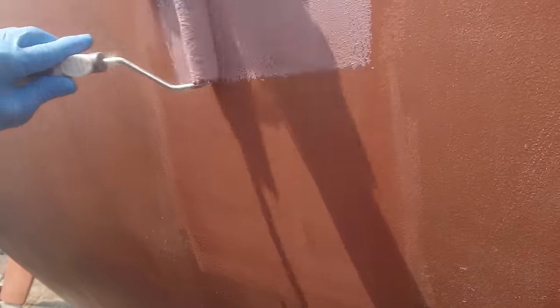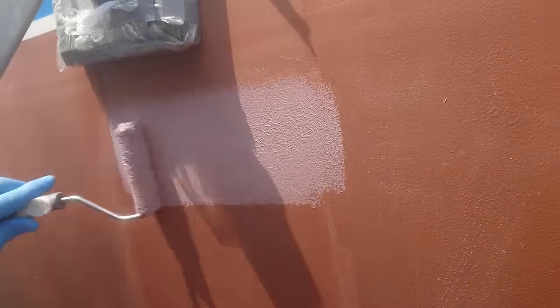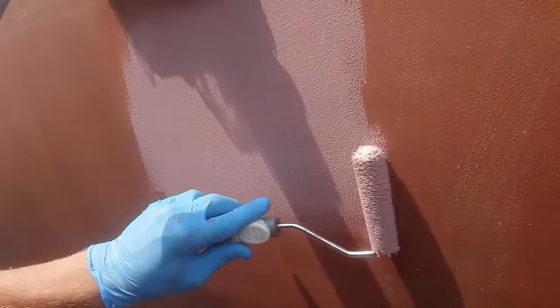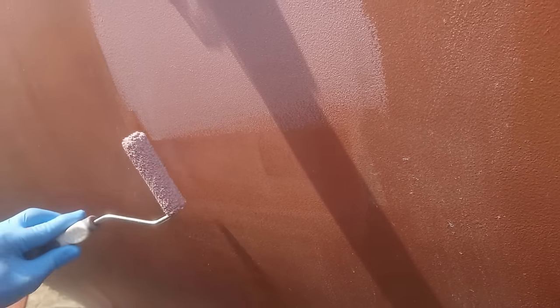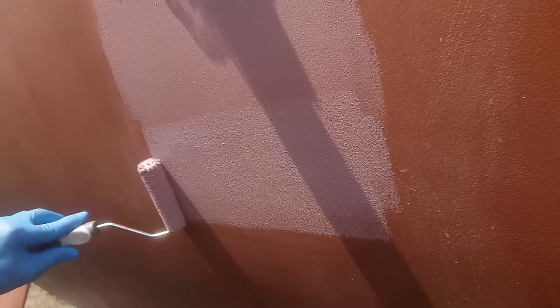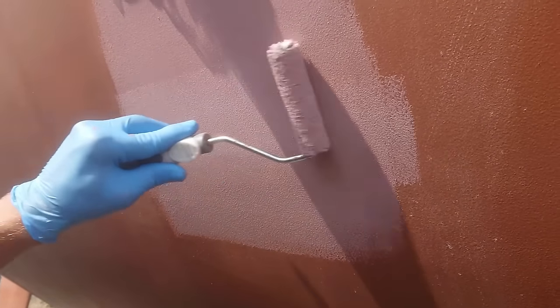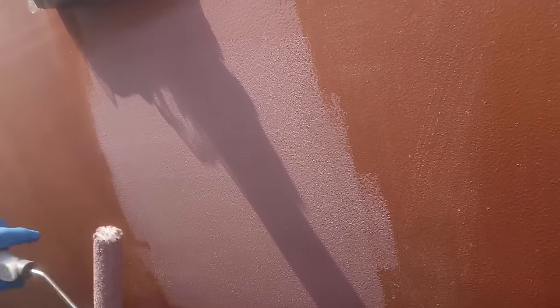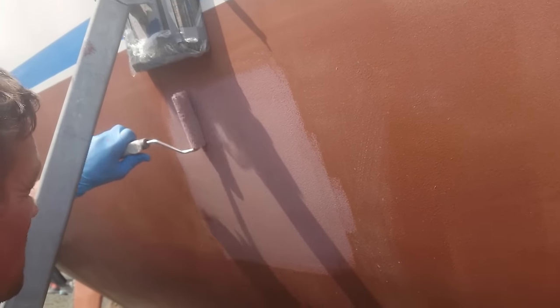We didn't want to use an antifoul containing chemical biocides, and there are antifoul paints available that only contain copper as the active ingredient. But even those paints leach that copper and the paint into the water, and they need to be removed and reapplied regularly. The copper in the copper coat is non-leaching, as it's held in place with the epoxy. And also, it's another layer of epoxy on the hull, that's a hydrophobic barrier to protect against osmosis. Anyway, I'm not trying to sell you anything here, I'm just letting you know our thought process for what we did and when we did it.